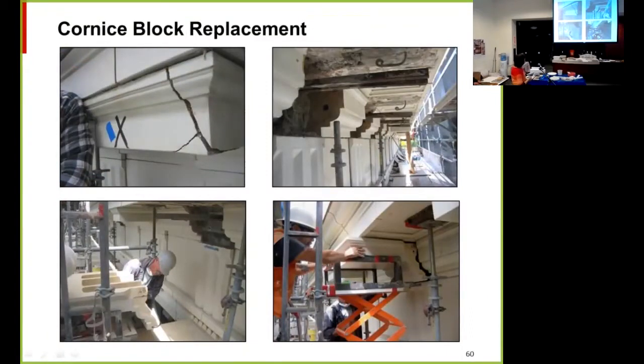So just a couple of examples of terracotta replacement. This was a cornice block that was seriously cracked because these angles that supported the cornice were corroding. So we had new blocks made. Here you can see the new blocks. And then we had new steel made and then filled these cells on the sides with grout and then just lifted it up, put the block in there and let it set.